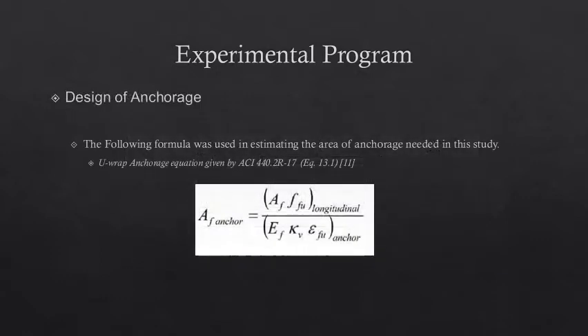This is the area of the CFRP anchors, and we took this equation from the ACI 440 guidelines, equation 13.1. Once we put it at the ends, with the same area we then distribute it equally along the span of the beam.